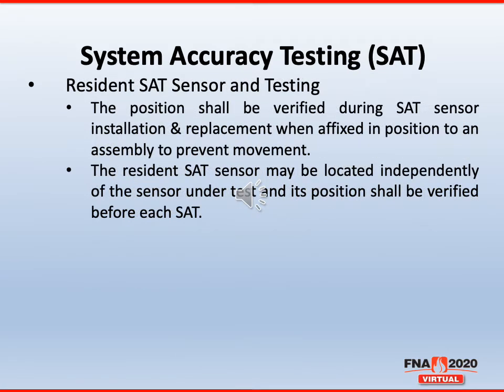In regards to the resident SAT sensor and testing, the position shall be verified during the SAT sensor installation and replacement when affixed in a position to an assembly to prevent movement. So in other words, you have to verify your resident SAT during your system accuracy testing to make sure that it hasn't moved. The resident SAT sensor may be located independently of the sensor under test, and its position shall be verified before each test. Again, you can have the resident sensor permanently placed in there and make sure that it doesn't move and verify it each time, or you can remove the resident SAT sensor but put it back in the same location as long as it's documented that it's verified in the same location.